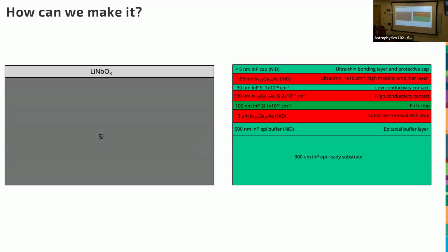So we grow this other wafer here. So we have one wafer here. This is either all lithium niobate, or in our more sophisticated devices, something like silicon with lithium niobate thin film. And then here we have this indium phosphide wafer. And we grow this series of epitaxial layers that are all lattice matched, so they can be nice and thick, and there's no defects.